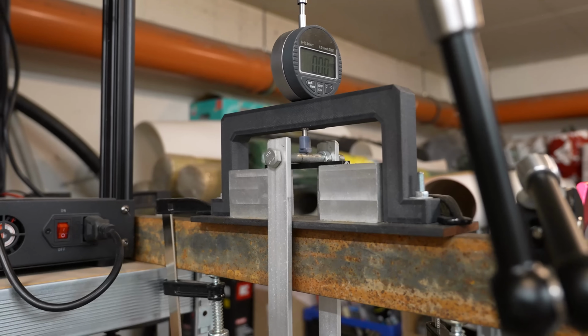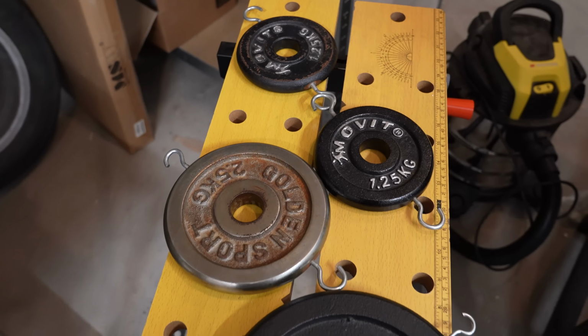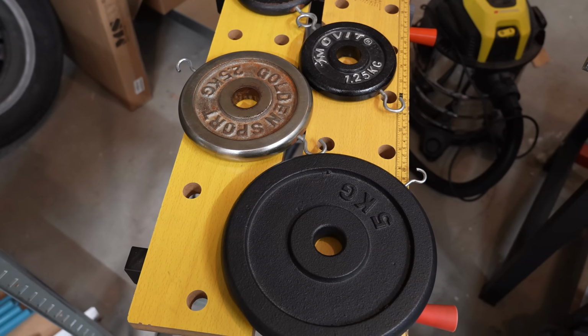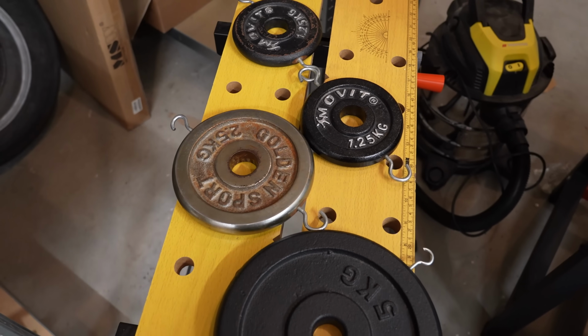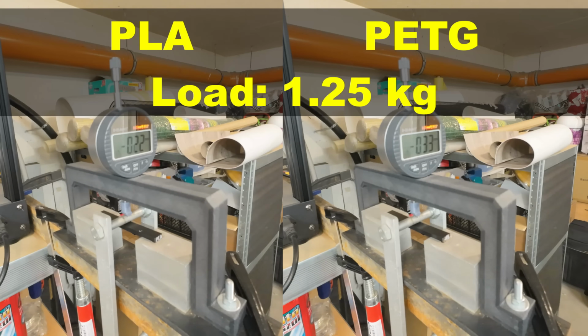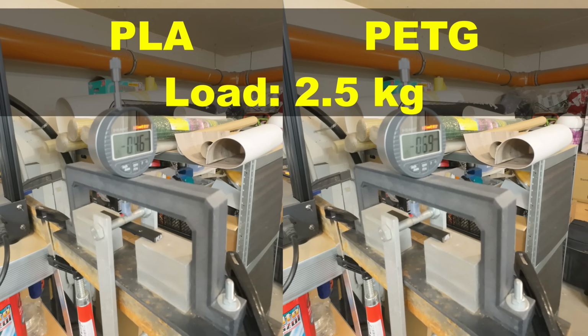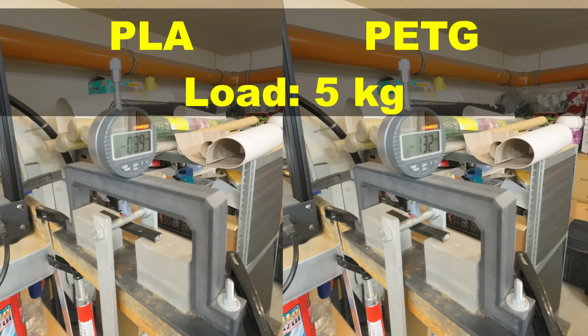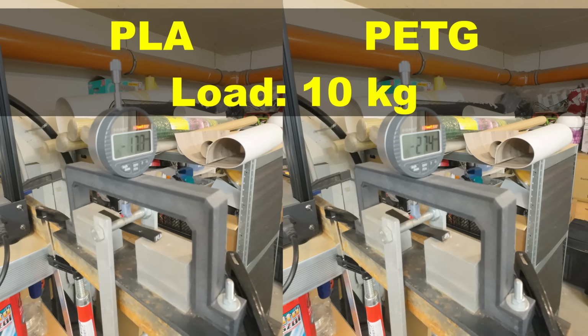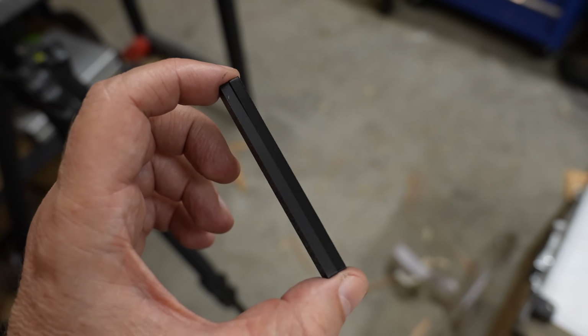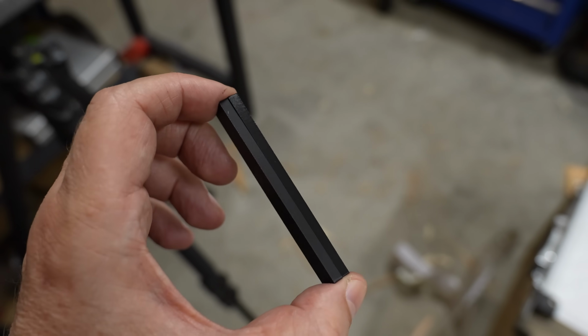3-point bending test. With these loads, which will be placed one by one, and I will measure the deformation after 1, 30 and 60 seconds. Deformation under 1.25 kilograms. Under 2.5 kilograms, 5 kilograms, still very minimal additional deformation during the time, and this is under 10 kilograms. No permanent deformation on them after this test.